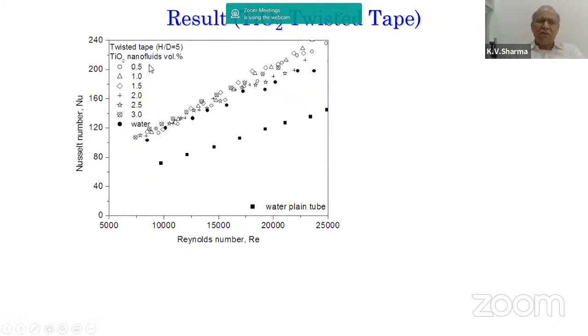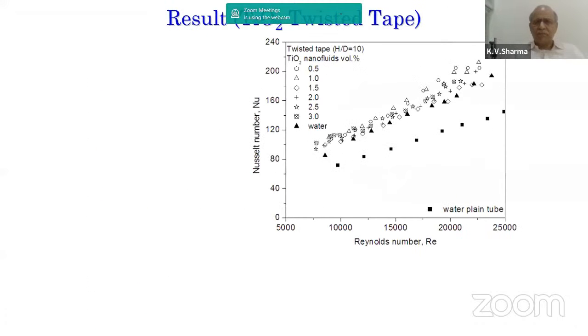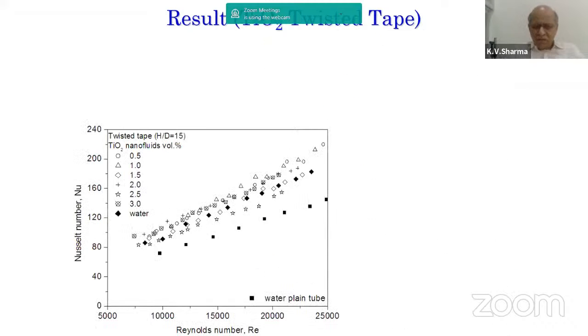So keeping H by D of 5, for TiO2 of different concentrations, when compared to flow in a plain tube, you see that for a twisted tape, the heat transfer coefficients have increased significantly. The Nusselt number is about 140 here, but here it has crossed 240. When the twist ratio has been increased to 10, the spacing increases and consequently the heat transfer coefficient decreases. So the values have come down a bit compared to the earlier one. In the third one, H by D is 15, it will come down. It has come to about 200.